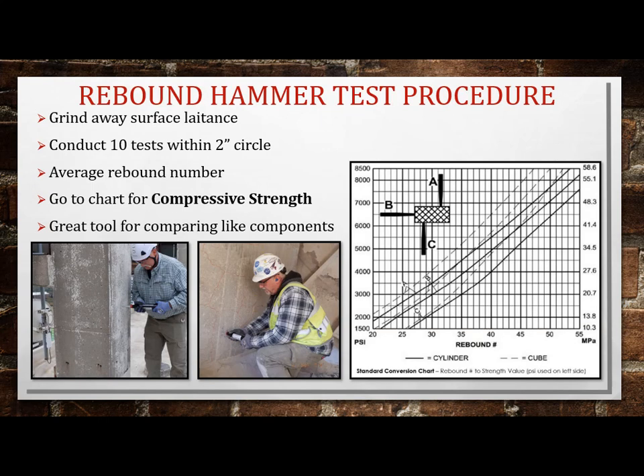So this is kind of the procedure. The first thing you do when you come up to a sample, this is more of a concrete test, but there is a masonry unit I'll show in a minute. It comes with a pumice stone, and so you would actually grind your test area. You get about a 2 or 3 inch diameter, and you grind that, you get away any laitance, any of that powdery dust, a little milky surface film. You get that off, so you just see your sand and your aggregate, and then you strike that area 10 times with your hammer, collect the data each time, you average that, throw out highs and lows, and then you take that number to the compressive strength chart, which is on the hammer.